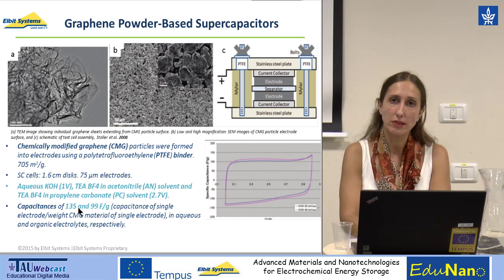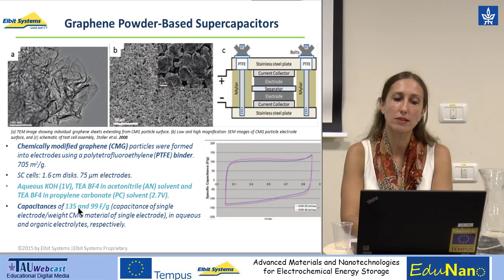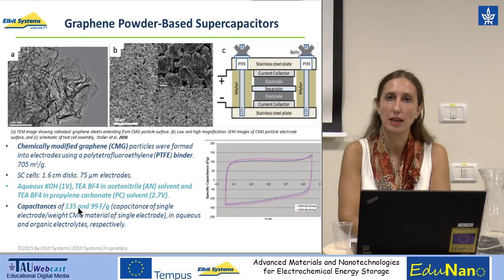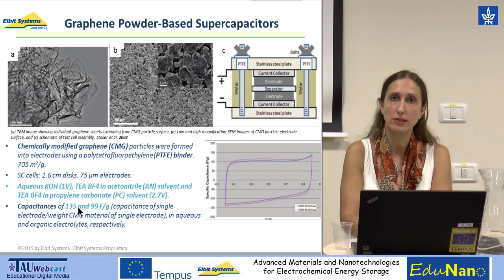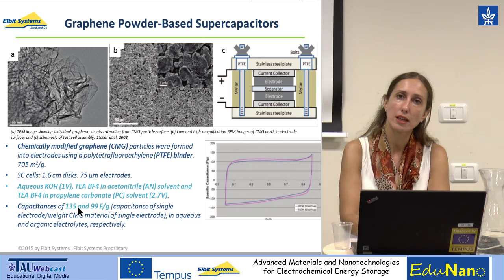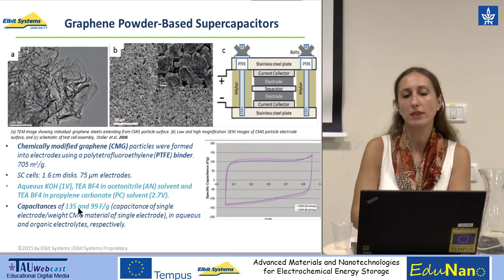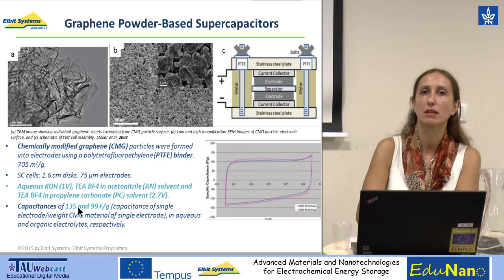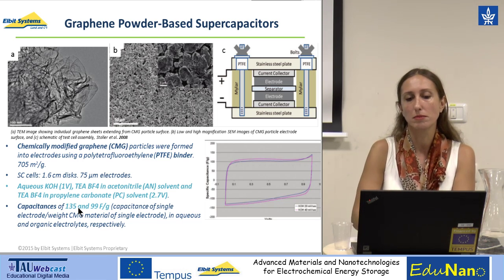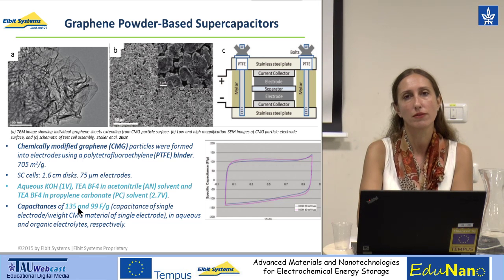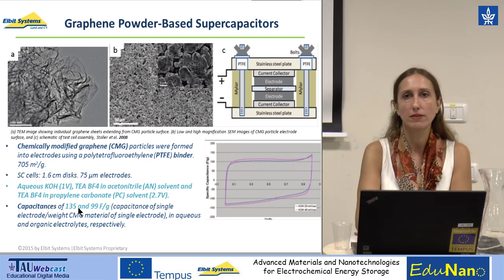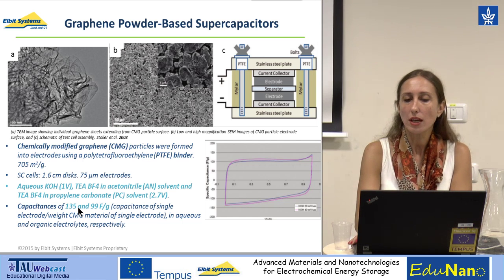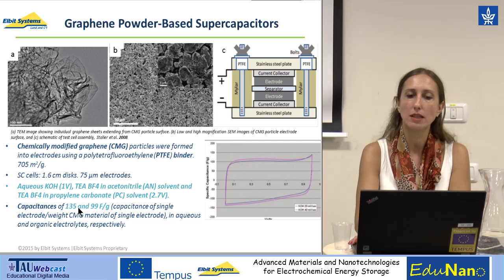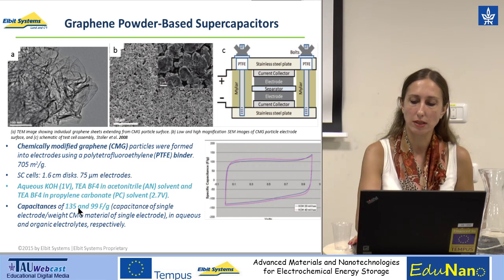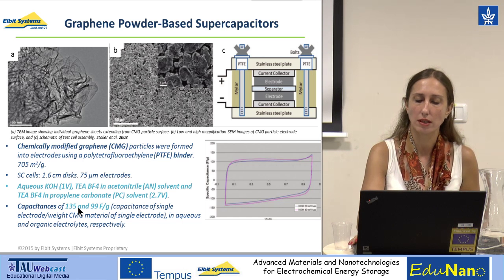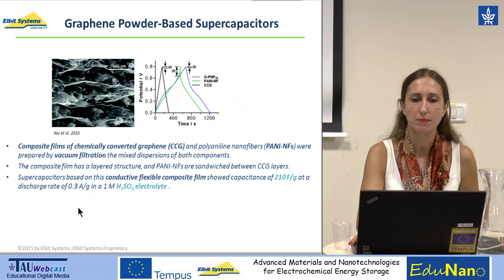What is interesting to see is that the capacitance for organic electrolyte based supercapacitors is relatively high. Usually with commercial activated carbons, you attain in organic supercapacitors capacitance values of 70, 75 farad per gram. So this could be indeed a substitute of activated carbon as an electrode within a supercapacitor device.